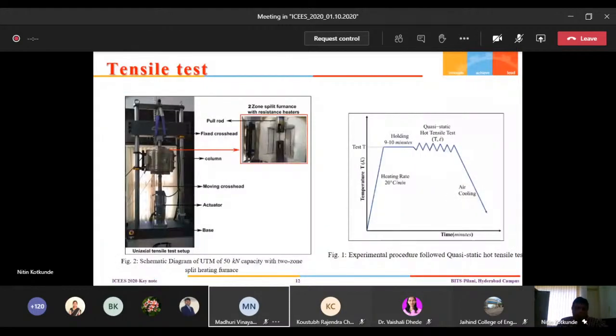Bismade, which is an Indian made, very sophisticated tensile test machine with a contact type extensometer, because the extensometer is very essential to capture the true values of stress and strain. We don't want engineering stress versus engineering strain here. We want true deformation for sheet metal forming applications to understand the real time behavior of a material. So we use the extensometer while testing, and this is the heating cycle we used. The heating rate is 20 degrees per minute, then a holding time of some minutes to assure uniform temperature throughout the specimen, and then we conduct the test, and then we air cool it.